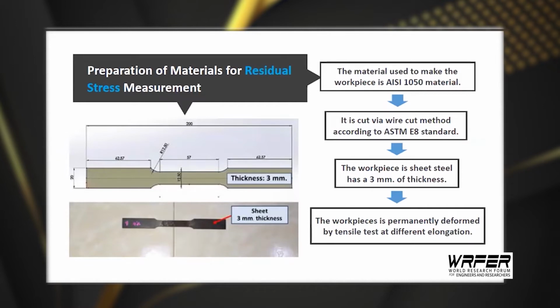The material used to make the workpiece is AISI 1050, cut via the wire-cut method according to the ASTM E8 standard. The workpiece is a sheet steel with a thickness of 3 millimeters. The workpiece is permanently deformed by tensile test at different elongations, beyond the yield point but not exceeding the ultimate point. That is, the tensile test is performed during strain hardening to achieve different levels of residual stress.